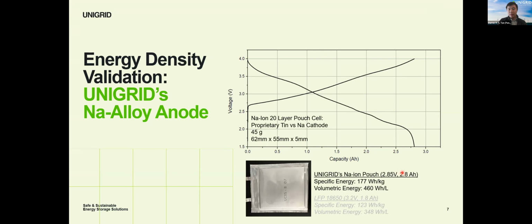And if we do the math on the energy densities, we get a specific energy of about 177 watt-hours per kg and 460 watt-hours per liter for the entire pouch itself. So if we put this beside a commercial LFP cell, doing the same math, it shows how a sodium-ion cell can be competitive with LFP.